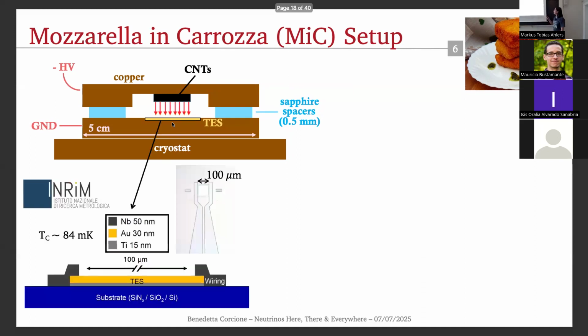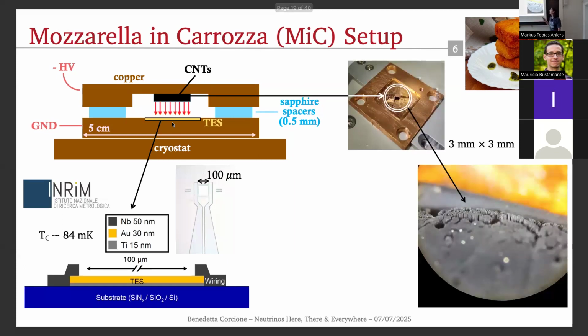Our TES was fabricated in INRIM in Turin, where I did all this research. It is a square bilayer made of titanium and gold with niobium wirings. It has a side of 100 microns and a critical temperature of 84 mK. So here is the TES, in front of which there are the carbon nanotubes on another copper plate. They are glued in front. And our sample of nanotubes is 3 millimeters by 3 millimeters.